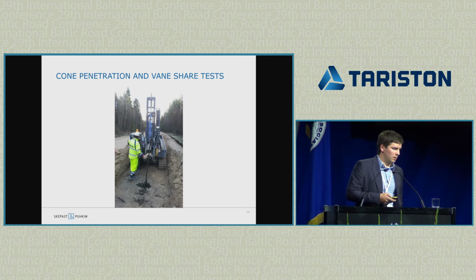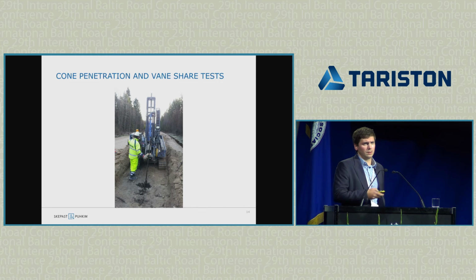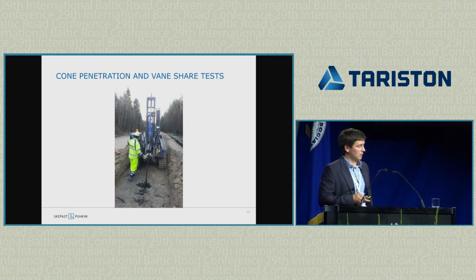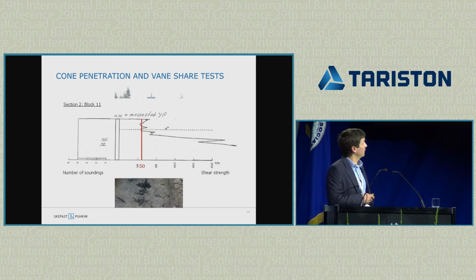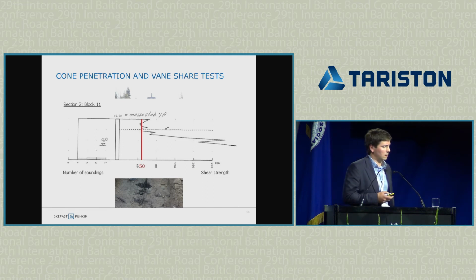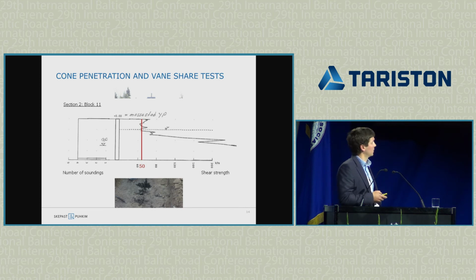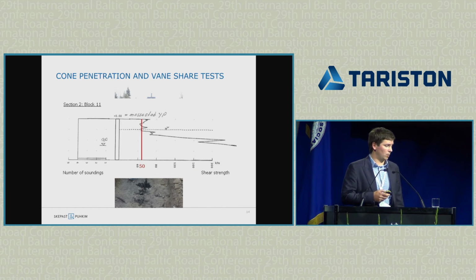Then we had cone penetration and vane shear testing. This was done also in different locations. First of them some 2-3 months after the mass stabilization works ended, and the idea was to find out if the stabilized layer became uniform and homogeneous enough. And we set ourselves a target value of 50 kilopascals. And we did the second cone penetration and vane shear testing about 1 year after the stabilization works ended. The results showed an increase of the uniformity and homogeneity of the mass stabilized layer.